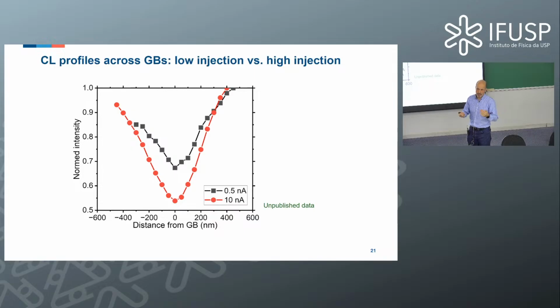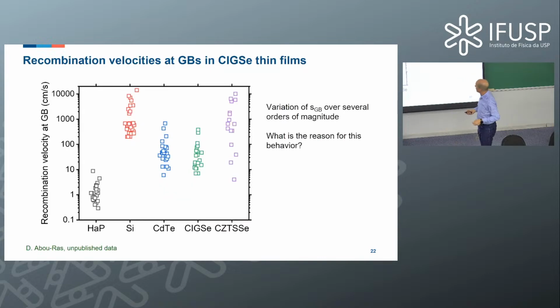So if we use a material like silicon, cadmium telluride, copper indium gallium diselenide, all of the established materials for photovoltaics, we would always have low injection conditions. And this is why one has to be extremely careful finding the right parameters for the measurement.